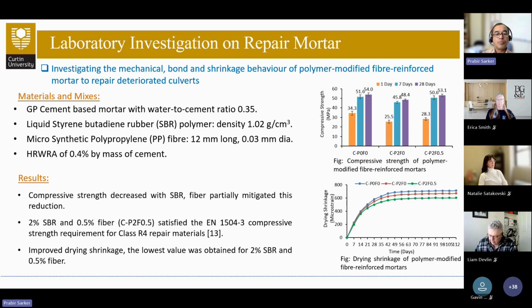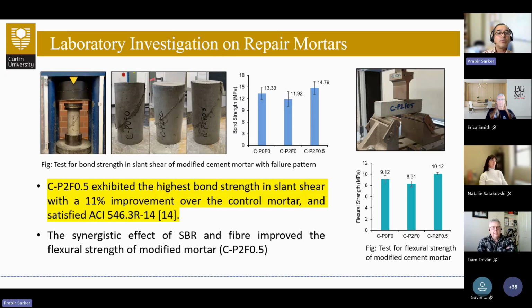That also improved the drying shrinkage, another very important parameter required for repair mortar, because high shrinkage will produce cracks at the early age of the repair, which may not be very effective. Then we also looked at some of the commercial structural mortars available in the market.